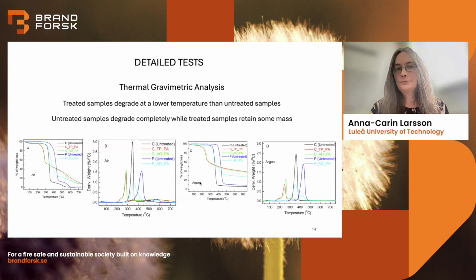In argon atmosphere, we don't get any ignition because we don't have any oxygen here. So we can see first some water disappearing, then the thermal degrading of the flame retarded samples, and then mass remains - almost half of the mass - while the untreated samples degrade completely.